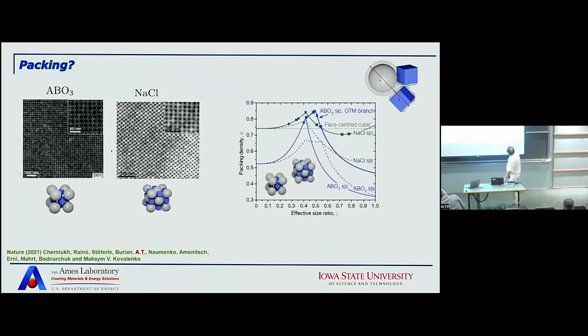And then here I want to mention that this is what the packing fraction looks like when you include these splayed configurations. And here, what you have is what they look like when you have only strictly hard shapes. And what you see is that the experiments agree very well with the maximum according to the splayed configurations. Not only that, if you don't include that, then this is where the point would be, again at a 50% packing fraction. In other words, all these splayed configurations are playing a fundamental role in predicting the structure of the lattice, and we can do that without any fitting parameters.